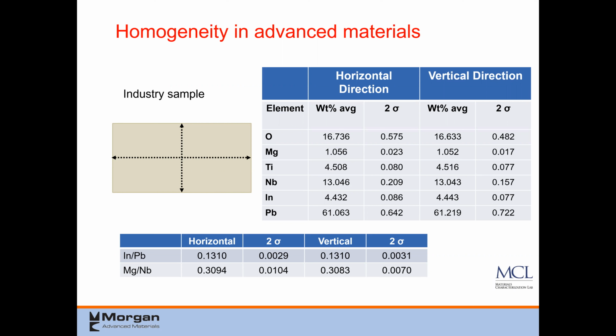These are boules of crystals that were grown, and I would get a whole bunch of these at a time that I would have to do these analyses for, to make sure that the ratios weren't varying more than a specified amount in either direction of growth. And so you can see some examples at the bottom. You can see in the horizontal and vertical direction that the indium lead is definitely exact in both directions, and the magnesium niobium within error is also exact.